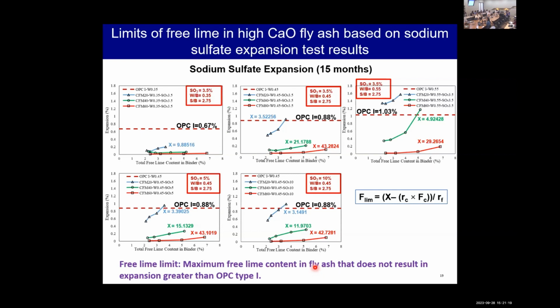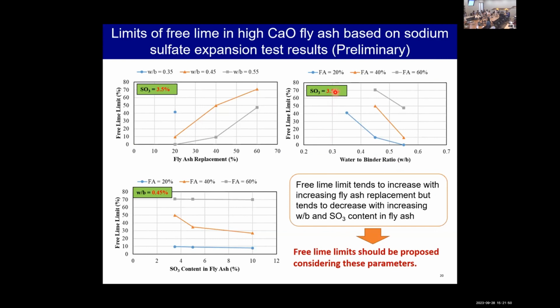We also tested sodium sulfate expansion, and from the result, we can see that even when the free lime content is increased, some values are still smaller than the OPC one. So for this data, we obtain the free lime limit with the concept that the free lime limit is the maximum free lime content in fly ash that does not result in expansion greater than OPC type 1. And from our preliminary study, we can get the free lime limit.